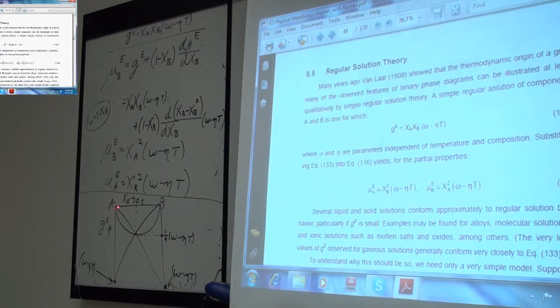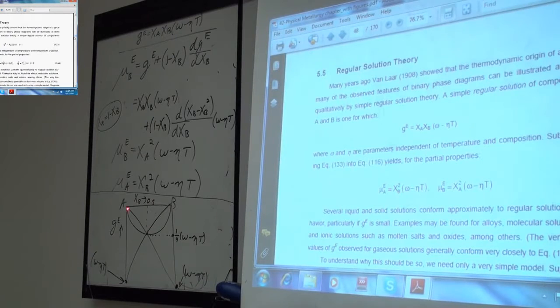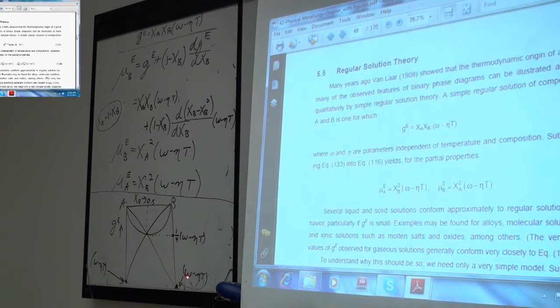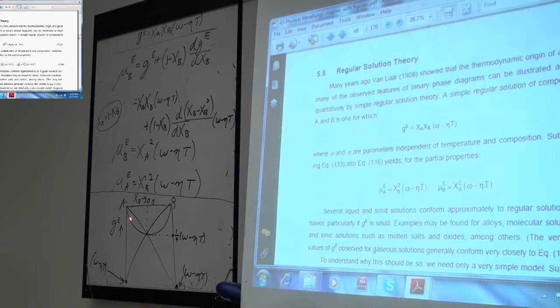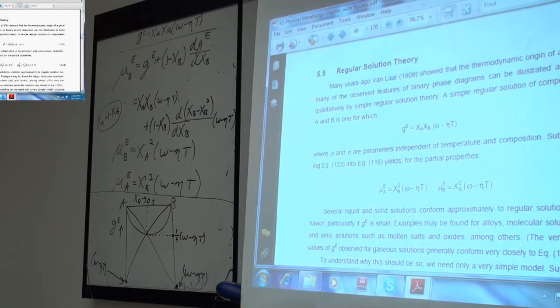So mu^XS_A will look like this. It'll be X_B squared, so when X_B is 0, mu^XS_A is 0. Clearly mu^XS_A is 0 for pure A. Then this is a parabola. Don't draw it like a parabola, but it is one, and it's finite at the end. In pure B, mu^XS_A is omega minus eta T, and mu^XS_B is a parabola going the other direction. They're symmetric, of course, and all three curves meet at the peak here at 50%. So that's what the partial properties will look like for a regular solution: all three are parabolas, for the integral excess and for the partials. Here I've drawn G^XS as negative. I've assumed omega minus eta T is negative, but they could also be positive, and then you just get positive deviations. The regular solution says that to a first approximation they're parabolic.